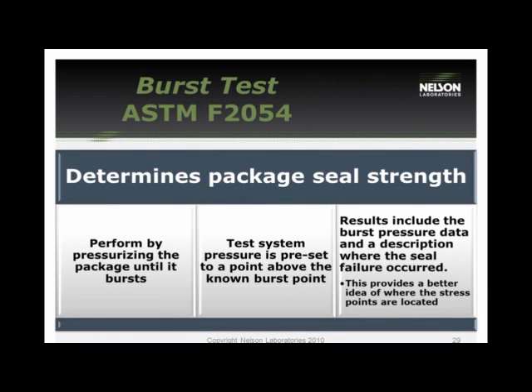The burst test is regulated by F2054, and it identifies the seal strength of the entire package and the weakest seal. The method for the test involves pressurizing the package until it bursts. The test system pressure is then preset to a point above that burst point. These are actually setup samples that establish the burst position. Then you start, we usually do a couple setup samples, and then we move into the actual test.